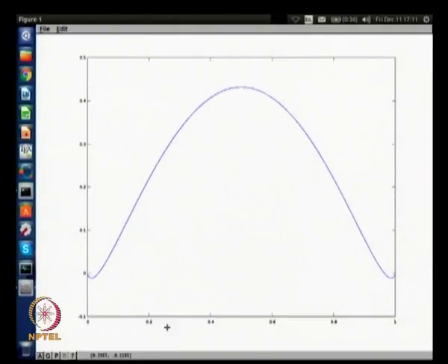In other words, as you go to the purer and purer systems, the configurational entropy contribution is going to increase, right. So, it is a very large number, and towards a purer component it is going to increase very steeply, and that is the reason why there will always be this dominance at the end points of the effect of entropy.